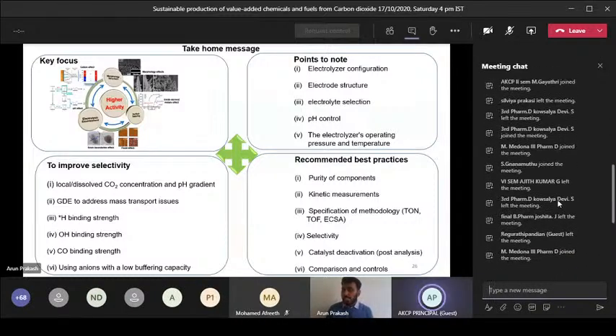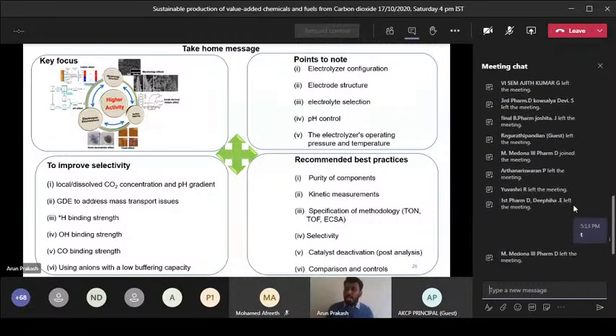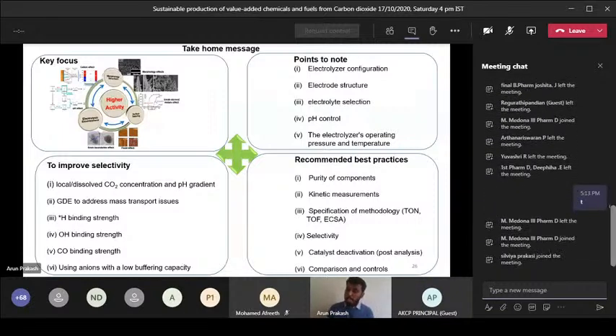If your electrolyte has some trace metal impurity, then you may not know whether the trace metal impurities present in your electrolyte are really catalyzing the reaction or your catalyst. So before doing this reaction, purify your electrolyte or get the pure form of the compound from Sigma Aldrich or any good chemical company available. You can get it with a 99% pure or a high assay product, and then you can prepare your electrolyte.